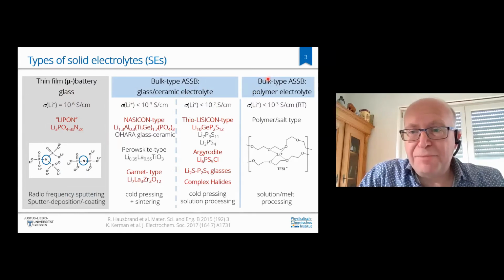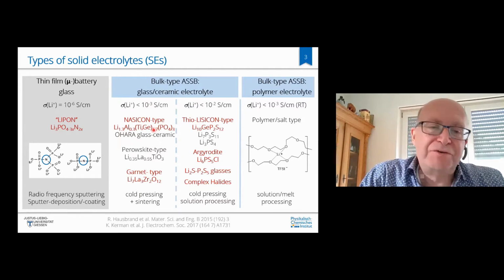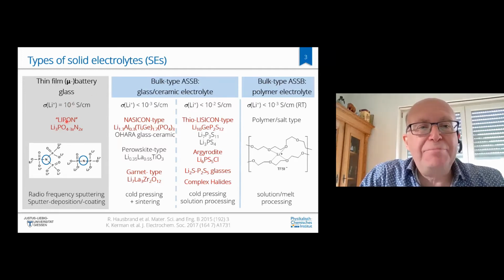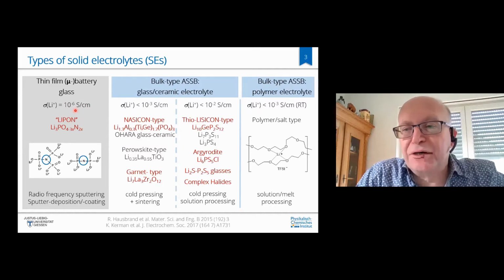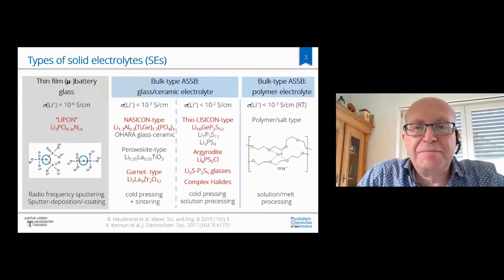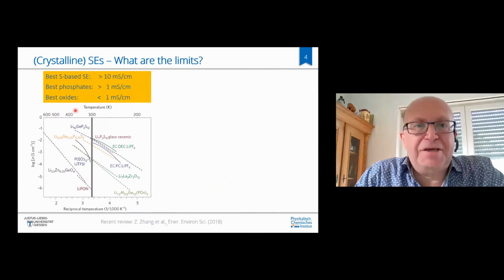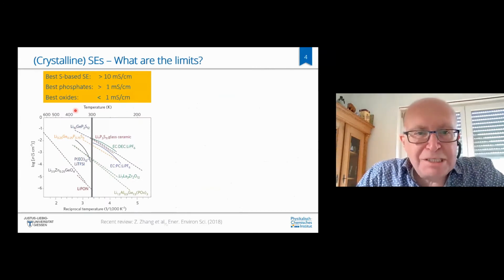Of course, polymer electrolytes have not yet reached these high conductivities, nor oxide or phosphate electrolytes. So I think 1 millisiemens per centimeter, or a few millisiemens per centimeter, is what you can reach with phosphates and oxides. Just for those who are familiar with thin film batteries, the LiPON, which is a nitrided lithium phosphate, the classic material for thin film batteries, has a really poor conductivity of only 1 microsiemens per centimeter. So analyzing the conductivity issue, I would say that's not an issue, but we will come back to that in